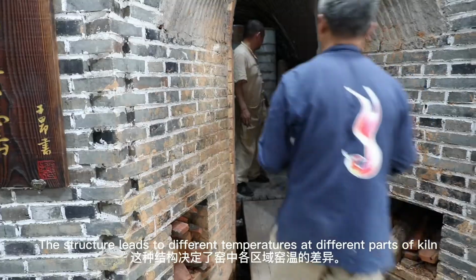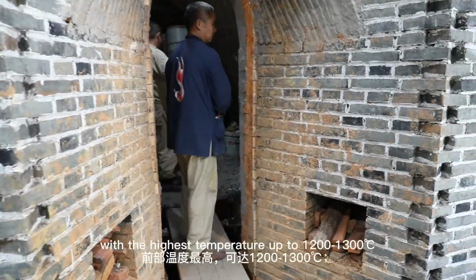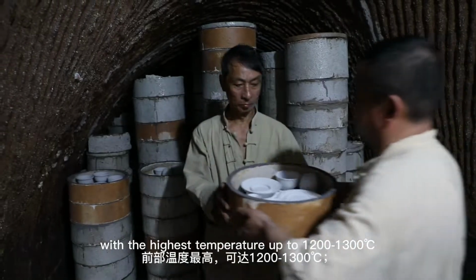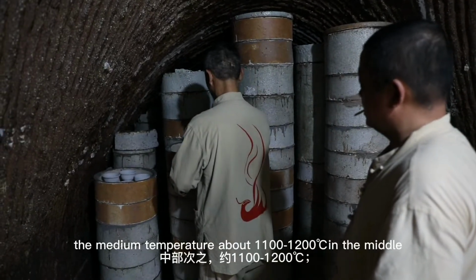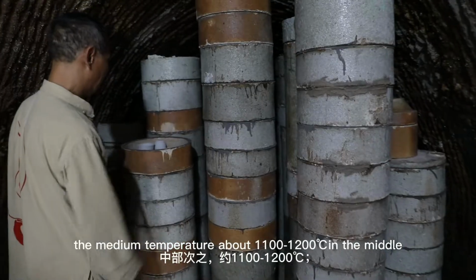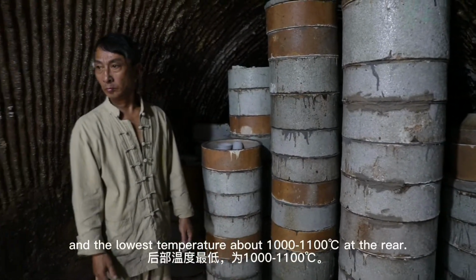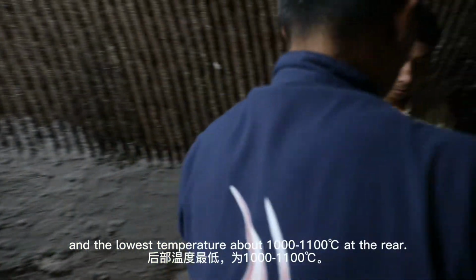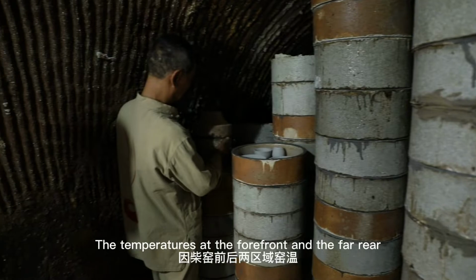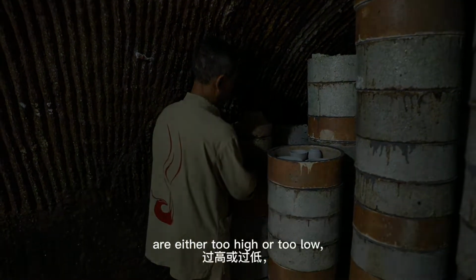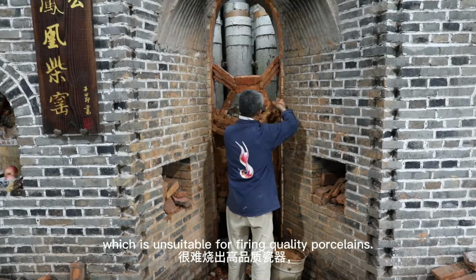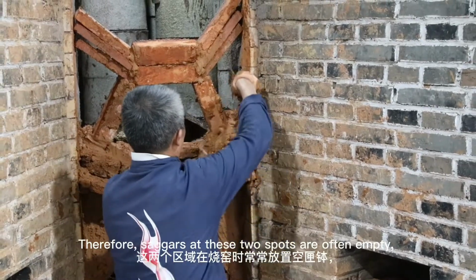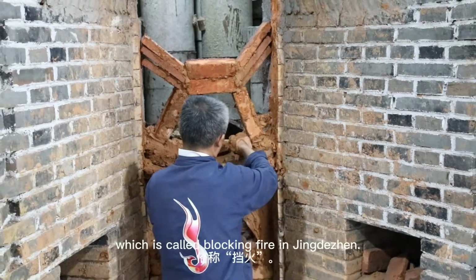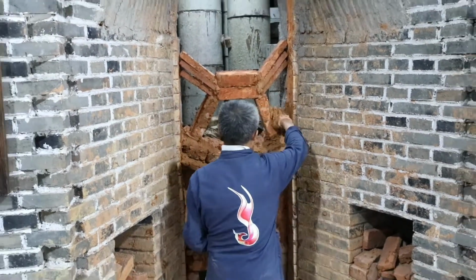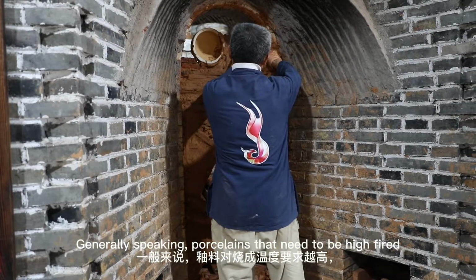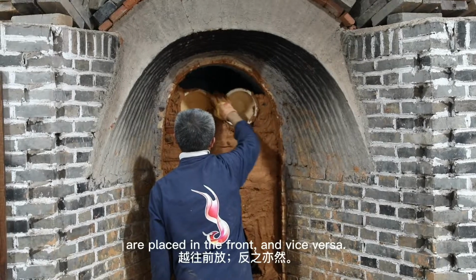The structure leads to different temperatures at different parts of the kiln, with the highest temperature up to 1200 to 1300 centigrade at the front, the medium temperature about 1100 to 1200 centigrade in the middle, and the lowest temperature about 1000 to 1100 centigrade at the rear. The temperatures at the forefront and the far rear are either too high or too low, which is unsuitable for firing quality porcelains. Therefore, saggers at these two spots are often empty, which is called blocking fire in Jingdezhen. Generally speaking, porcelains that need to be high-fired are placed in the front, and vice versa.